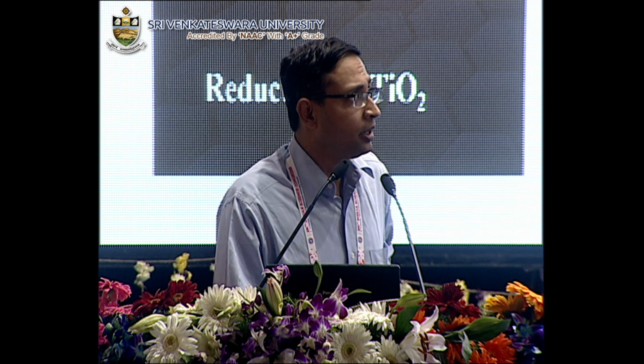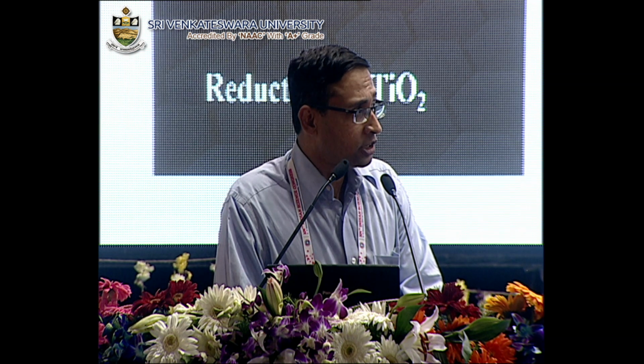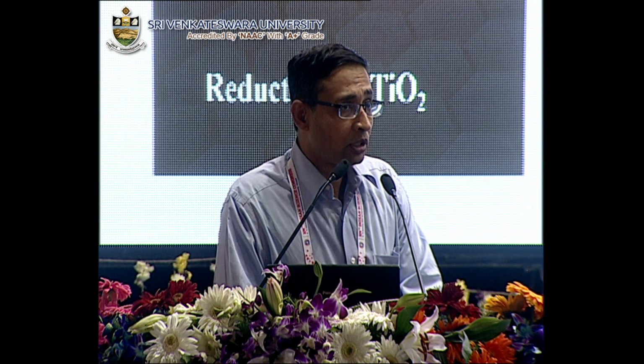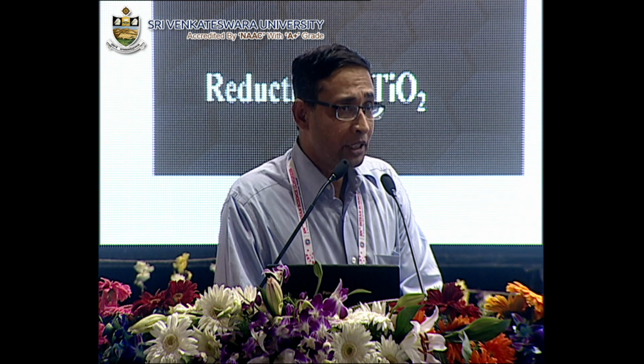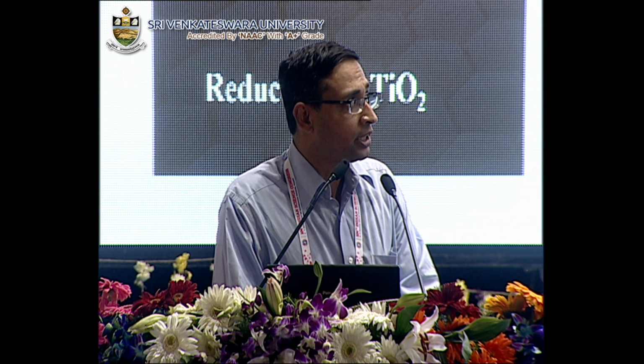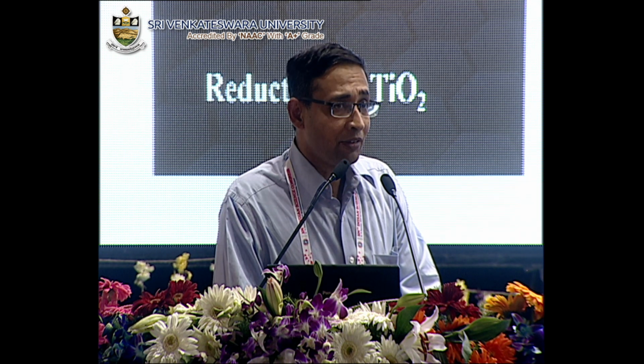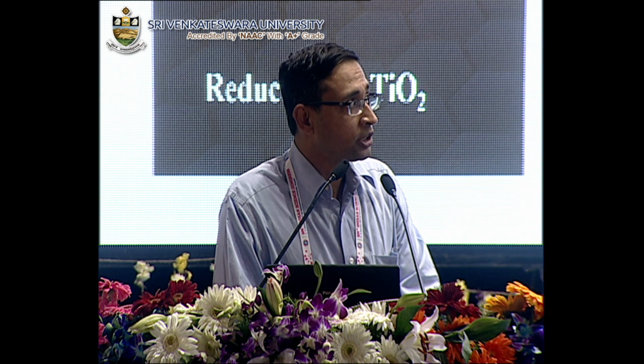If you see here, there is the black background, which is the carbon, and this white circle, which is the TiO2, the photocatalyst. Now the electron which is dormant in the valence band is excited to the conduction band, and the electron is now available for some reaction. When the precursor chloroplatinic acid comes near, the electron travels to the chloroplatinic acid and reduces it to platinum.